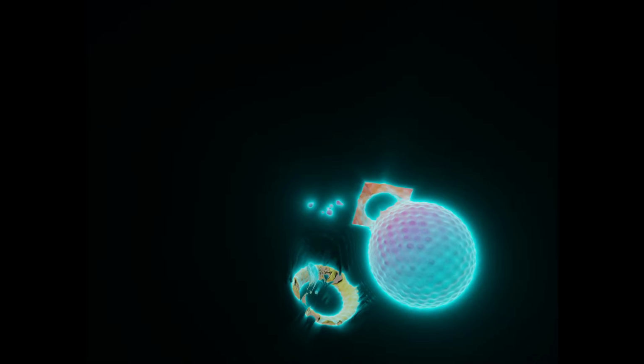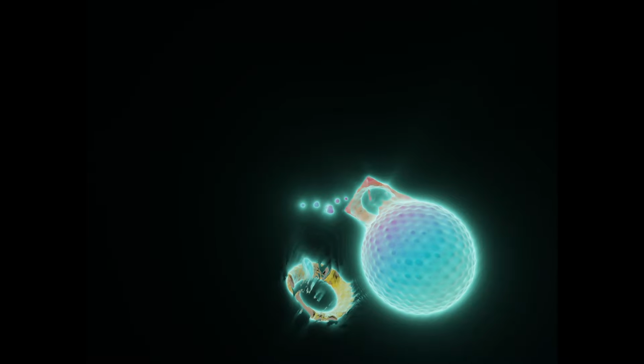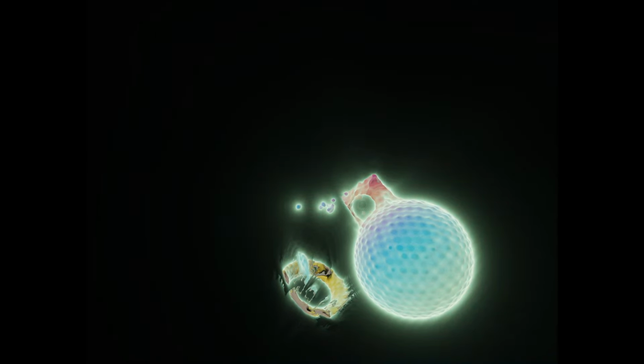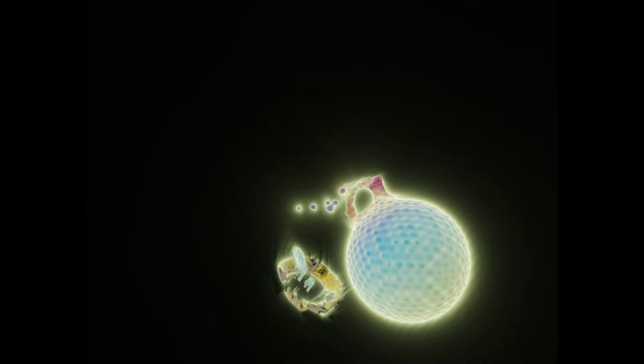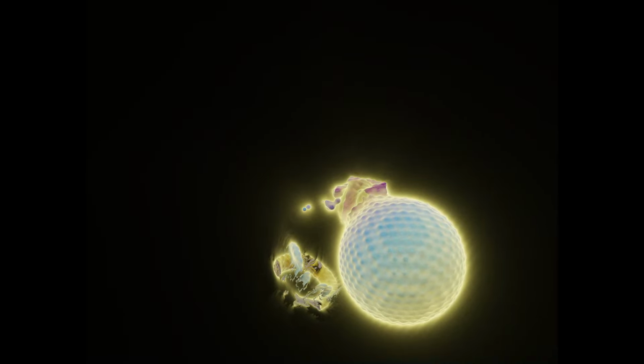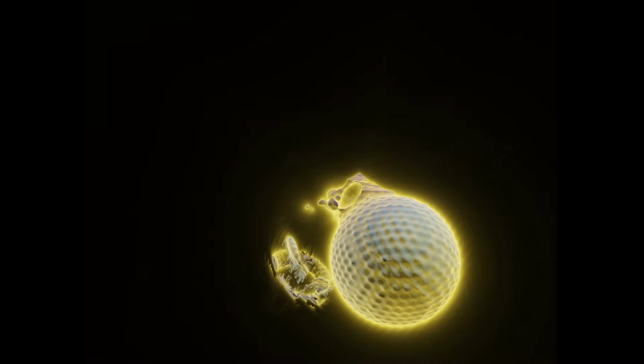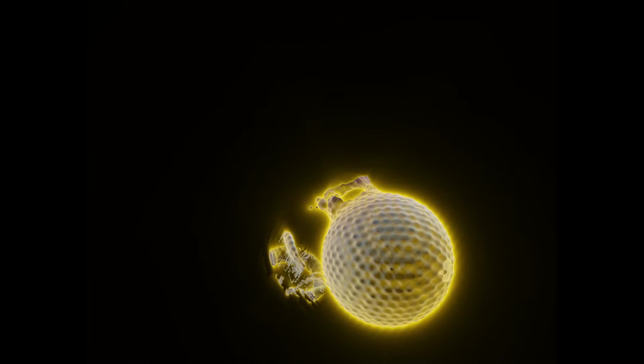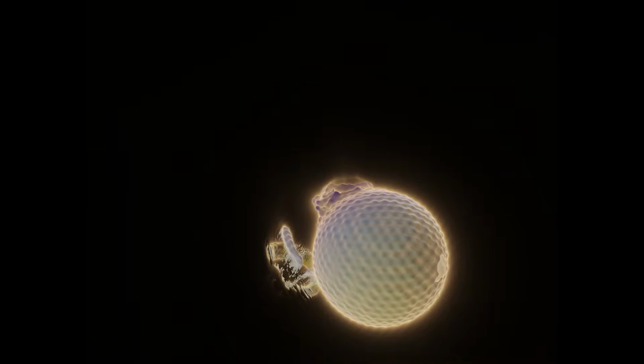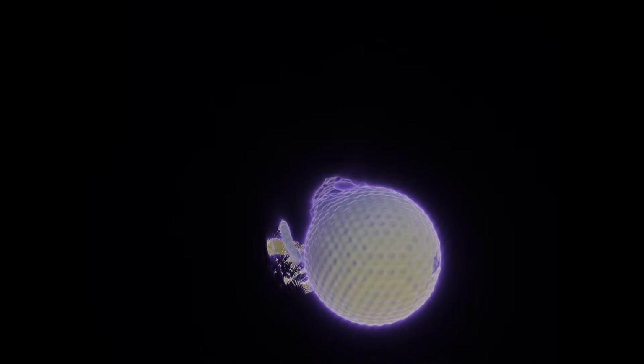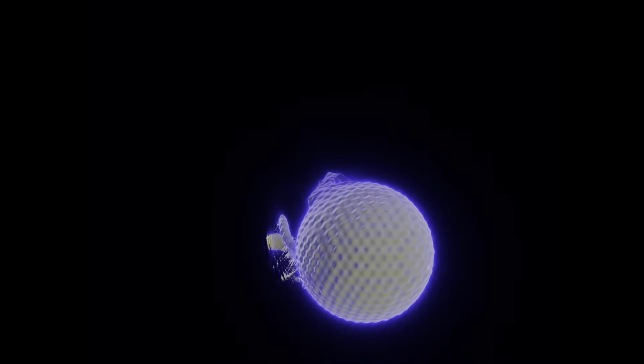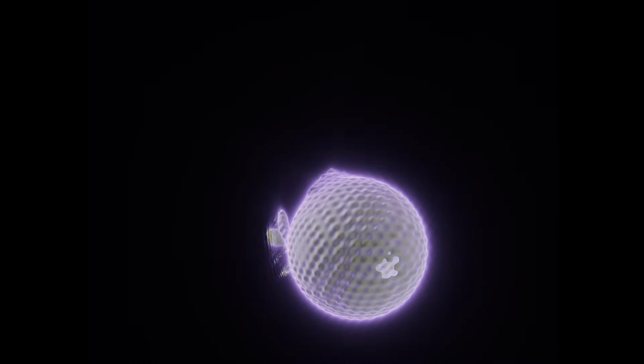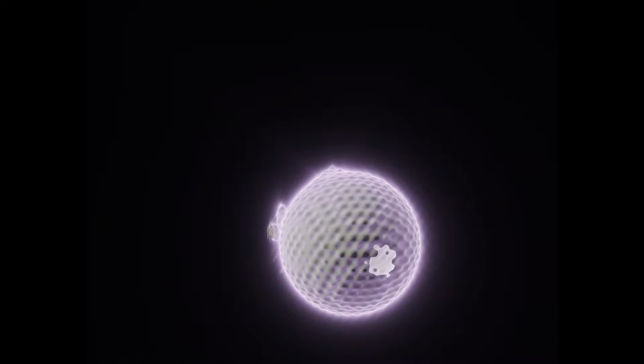Okay, so contacts are one hurdle. What else? You mentioned doping. Right. Doping, adding impurities to control whether the semiconductor is N-type or P-type. In silicon, we use ion implantation, basically shooting high-energy ions into the crystal. Doesn't sound very gentle. It's not. And it's totally unsuitable for atomically thin 2D layers. You would just blast them to pieces, like trying to etch fine details onto a single sheet of paper with a sandblaster. Way too destructive.